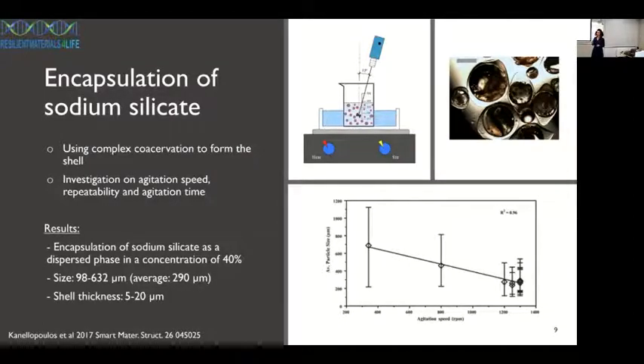A way of doing that was creating an emulsion with sodium silicate in oil, and then the deposition of the shell was at the interface of the oil. So we are not talking about a capsule that is purely sodium silicate inside. We are talking about around 40% of sodium silicate dispersed in an oil phase, and then encapsulated with a gelatin gum arabic shell. In this production, the average size was 200 to 290 microns, and the shell thickness of this gelatin gum arabic system is around 5 to 20 microns.